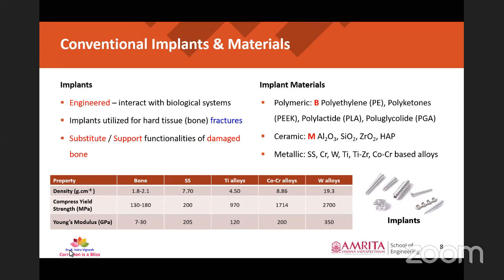For example, we could typically take titanium alloys, which is conventionally used as an implant material. We could observe that the density of titanium alloy is more or less twice that of the density of bones. Added to the compressive yield strength, the bone has a compressive yield strength of 130 to 180 megapascal, but the titanium alloys will have around 970 megapascals. Young's modulus too, when it comes towards bone, it will be 30 gigapascals, and if it is titanium alloy, it is going to be around 120 gigapascal, which is 4 times higher than that of the requirement.